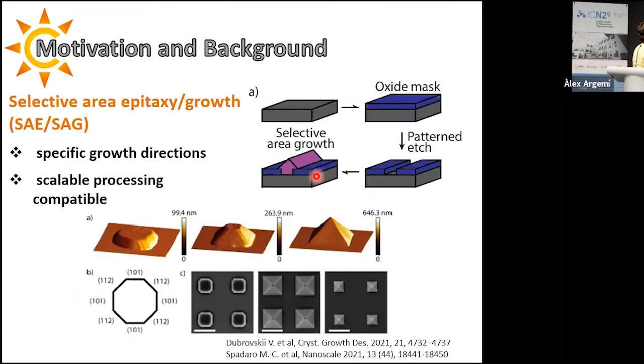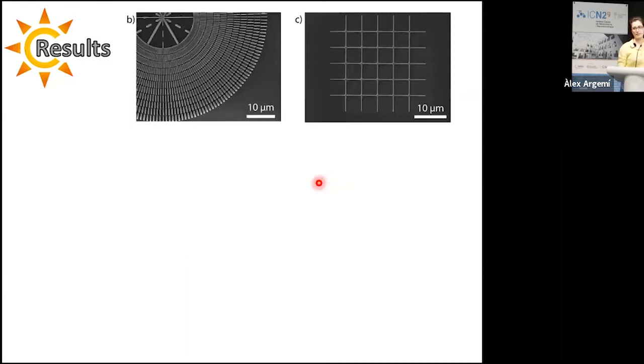Recently, another synthesis route has been introduced, which is selected area epitaxy or growth, in order to obtain the so-called horizontal nanowires. The methodology is sketched here. We start from the substrate of interest, and on top of it, we deposit an oxide mask. Then, thanks to lithography, we can create apertures on the mask. These apertures can be either circular, obtaining the so-called nanopyramids depicted here, or they can have specific orientations along the substrate, obtaining the horizontal nanowires here depicted. And this is the case that we investigated recently.